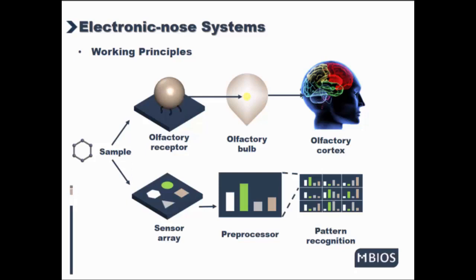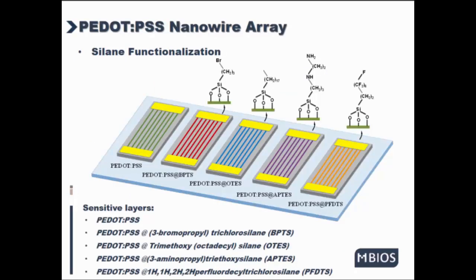Due to the high surface to volume ratio, the nanowire gas sensor has become a promising candidate for the e-Nose system. So by using the NAMIC approach, we have fabricated a PEDOT:PSS nanowire sensor array e-Nose system. The e-Nose system includes a non-functionalized PEDOT:PSS nanowire sensor and 4 other nanowire sensors functionalized with different kinds of gas sensitivity materials. And actually, the sensor response could be tuned by the introduced groups.